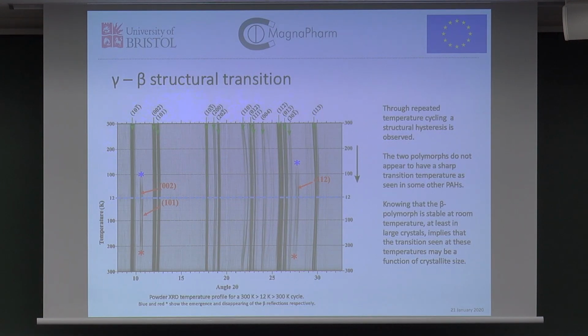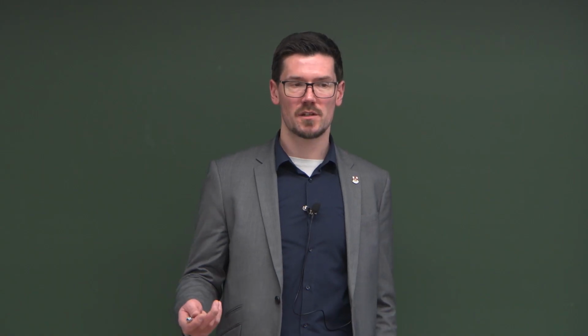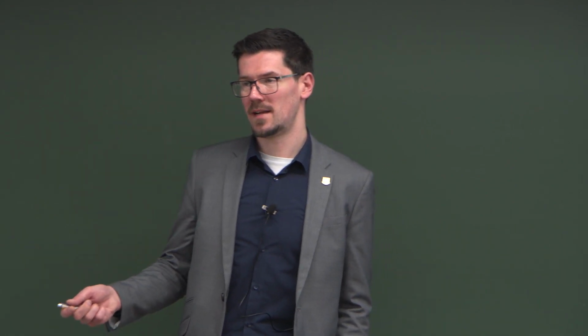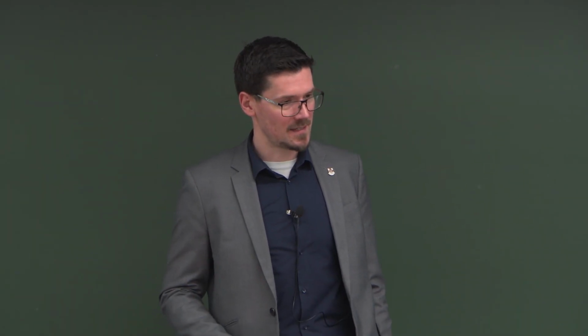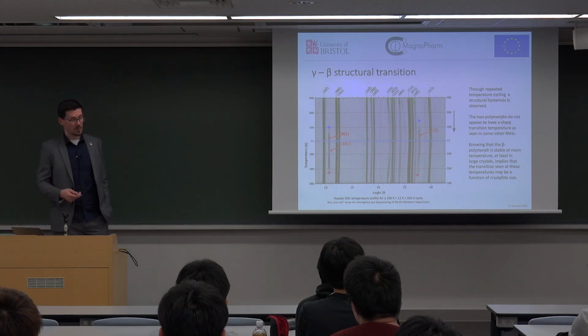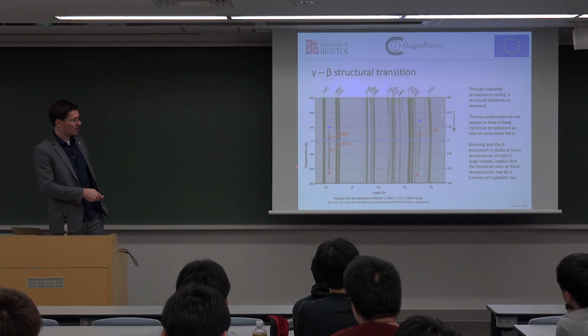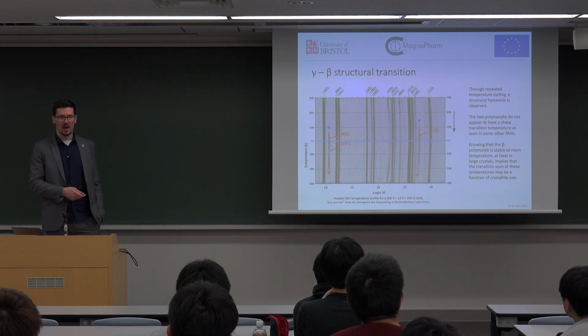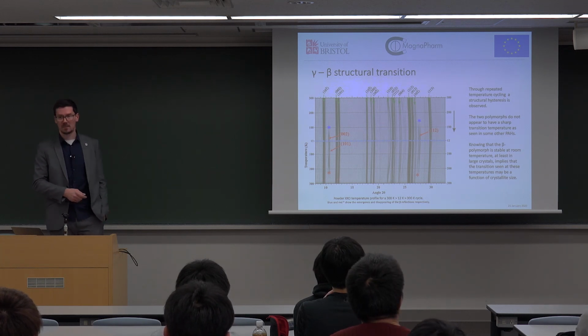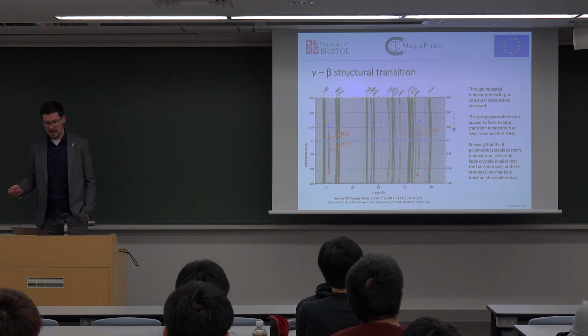And you can see, as marked by the blue asterisks, we actually see an emergence of peaks appear. Here and here, at slightly different temperatures, but these indexed perfectly to what I showed you earlier, the 002 and the 101 and the 112 of the beta phase. So it shows that there is a partial conversion of gamma coronene to beta coronene as we lower the temperature. Also, something that was kind of surprising was that they appeared at a temperature about 100 degrees lower than that at which they disappeared, which we didn't expect. So there's some kind of structural hysteresis.